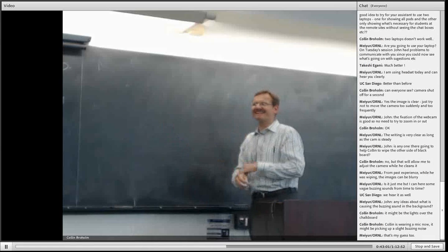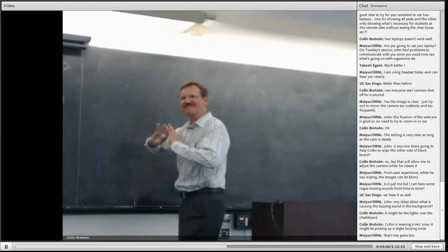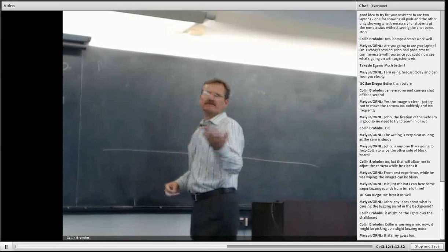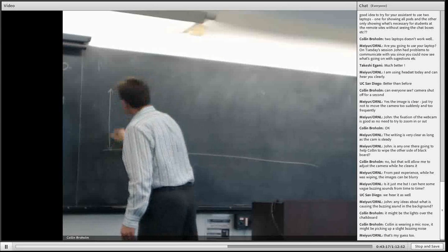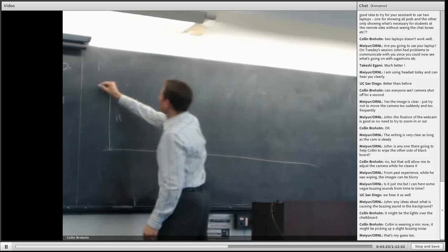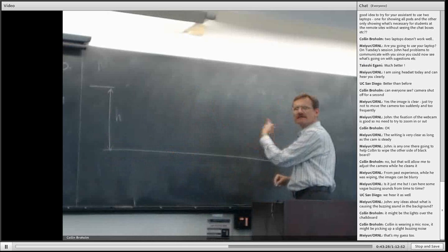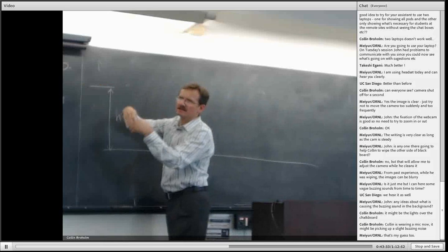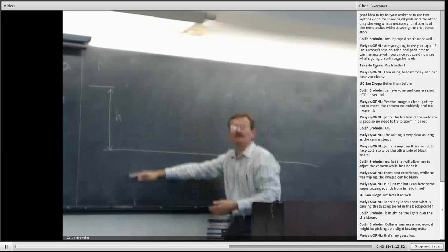But there's an even more elegant way of proceeding, which is just really beautiful. So the idea is the following. You create a surface of the material whose scattering length you'd like to measure. And then you arrange for a situation in which the height between the location where the neutron will emerge and the surface of the material can be varied. Now, typically, the height of the neutron beam will be somehow fixed because it comes from a reactor, from a guide network or something. So you could lower the surface appropriately, come up and down.